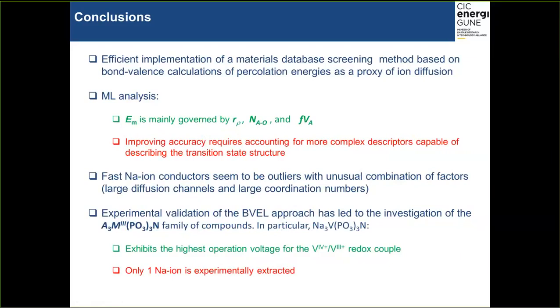In contrast to what is observed for the lithium compounds, fast sodium ion conductors seem to be outliers with an unusual combination of factors: large diffusion channels and large coordination numbers. And this will imply that the number of fast sodium ion compounds is significantly lower than the number of lithium ion conductors. From the experimental side, we validate with the bond valence energy landscape approach the investigation of this family of compounds, and in particular this vanadium-based one, which exhibits the highest operational voltage for the vanadium 3+/4+ redox couple, but unfortunately only one sodium can be experimentally extracted. With that, I would like to thank you for your attention, and I will be happy now to answer any questions you may have. Thank you.